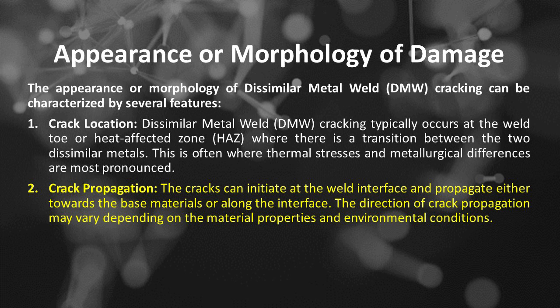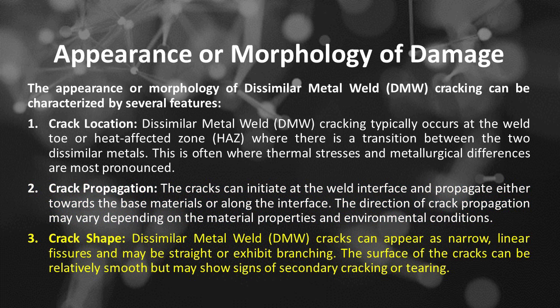Number 2 is crack propagation. The cracks can initiate at the weld interface and propagate either towards the base materials or along the interface. The direction of crack propagation may vary depending on the material properties and environmental conditions. Number 3 is crack shape. DMW cracks can appear as narrow, linear fissures and may be straight or exhibit branching. The surface of the cracks can be relatively smooth but may show signs of secondary cracking or tearing.